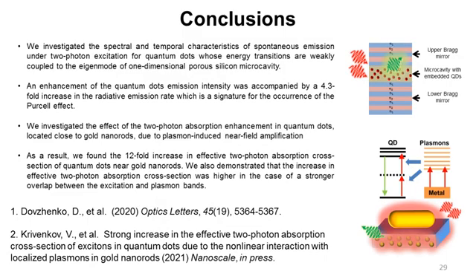In conclusion, we have investigated the two-photon excitation of quantum dots whose energy transitions are weakly coupled to the resonant mode of either porous silicon microcavity or to the plasmon mode of the gold nanorods. We found that inside the porous silicon microcavity, the radiative rate of the two-photon excited quantum dots accelerated by a factor of 4.3, and the two-photon absorption efficiency was increased by a factor of up to 12 near the gold nanorods. As an outlook, in the future one can combine these two effects in one nanostructure, thus significantly improving the photoluminescence of quantum dots under two-photon excitation.